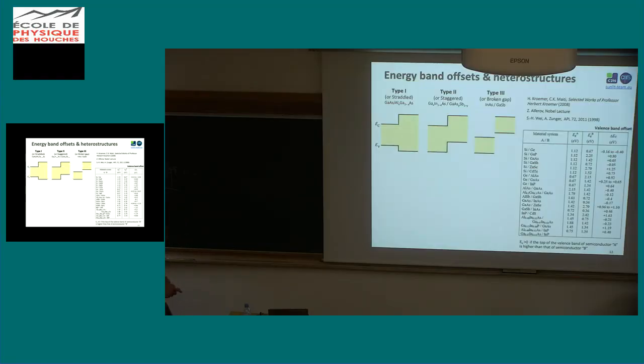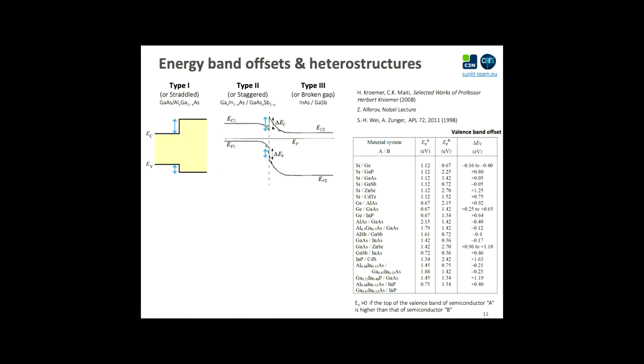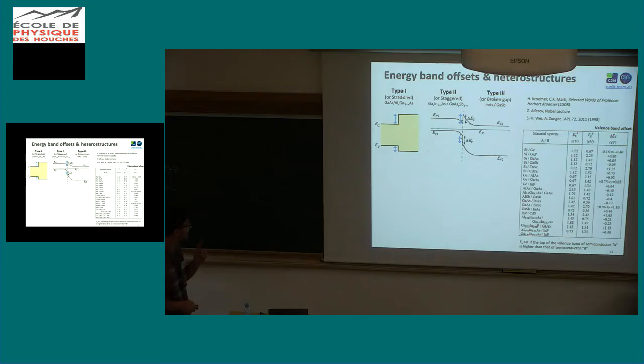And of course you can measure, and it's not trivial at all, or predict experimentally, theoretically, the band alignment of different materials with respect to the others. So this possibility to create heterostructure, I want to stress a point that sometimes is forgotten by students, is that whenever you dope your semiconductor, you do not change the band offset in between, for example, the conduction band of the first material and the conduction band of the second material, at least not at the interface. You preserve it here. Of course, you will align the two in the bulk, so don't forget this.